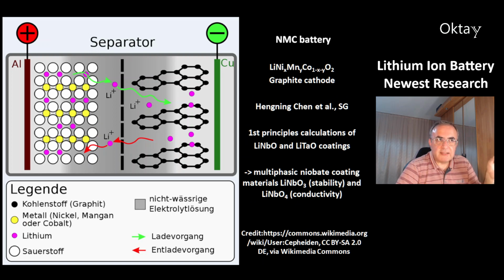There's another type of battery, that's the NMC battery, lithium, nickel, manganese, cobalt oxide. This type of battery has, for example, a graphite anode. There's a work of Heng Chen and colleagues from Singapore. They made a first principles calculation of lithium niobate and tantalate coatings. And they found out that a multiphasic niobate coating of lithium NbO3 gives stability, and lithium NbO4 improves the conductivity. That's the best combination according to these scientists.